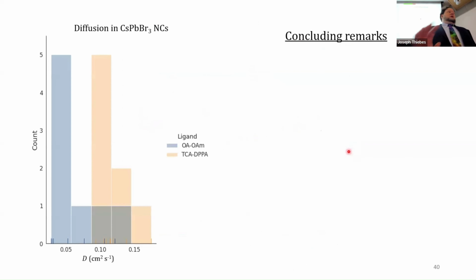So we took a bunch of diffusion measurements on these, about 8 for each system. And this is a histogram of the diffusion coefficients that we calculated from each one. And it looks like, in almost all the cases, the conjugated ligand, the TCA-DPPA one, is diffusing faster. So this was very encouraging. And we started thinking, well, gosh, we really have something here.